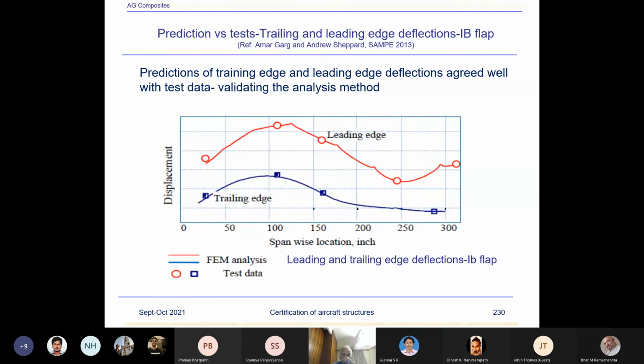Next one, the displacements. Using LVDTs at various locations, the trailing edge and leading edges, because you predict the deflections using finite element methods, and then compare using the test. What happens when you are using a finite element? There could be differences in the analysis because the stiffness which you are representing using the finite element methods may not be exactly the same. The laminated stiffnesses could differ from one point to another point, and that will change the deflections. However, again, the requirement was within plus minus 5% for the FAA requirements. And then engineers had to work in order to match the stiffnesses exactly to what the test was showing and the analysis showing. And you can see the result, they're pretty good.